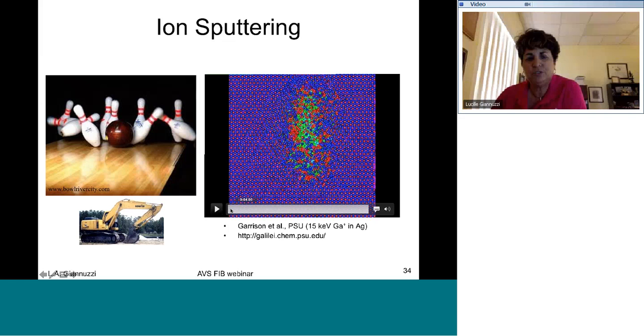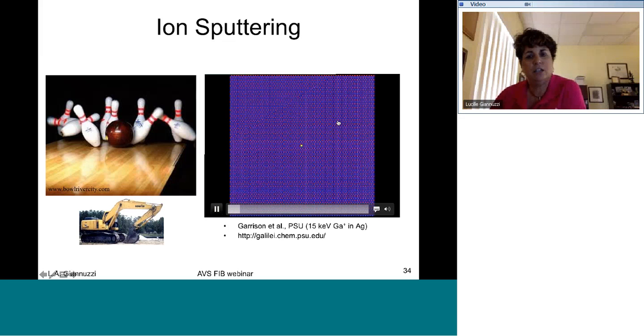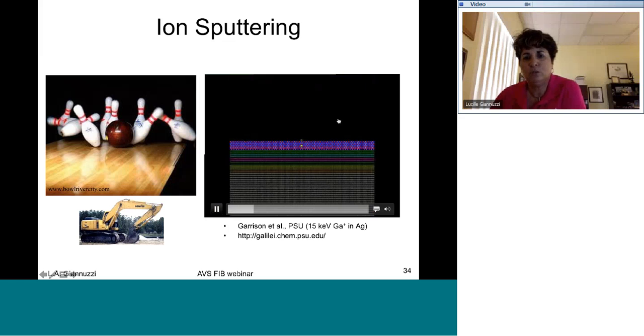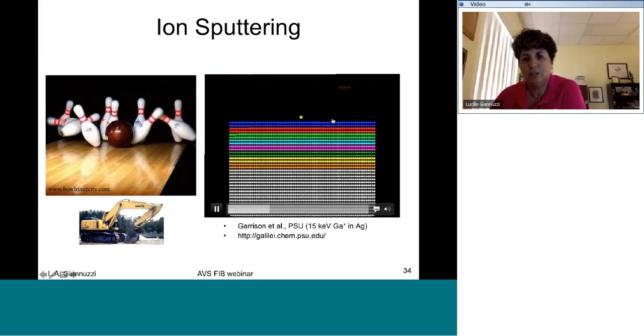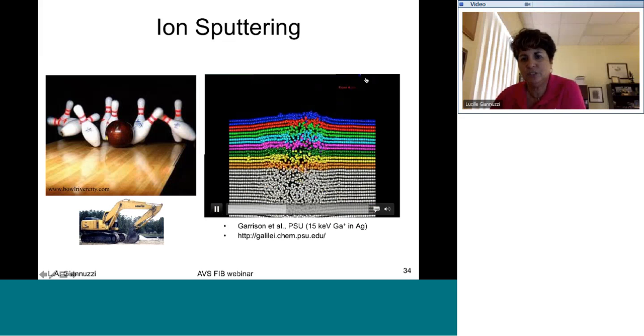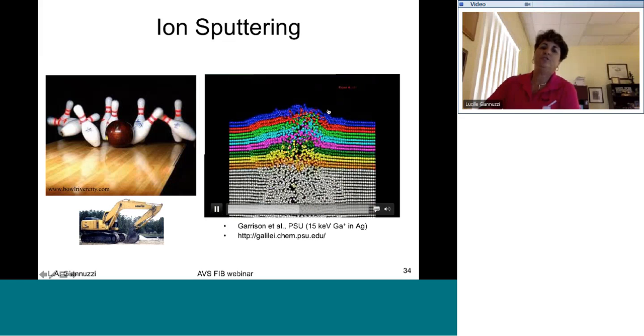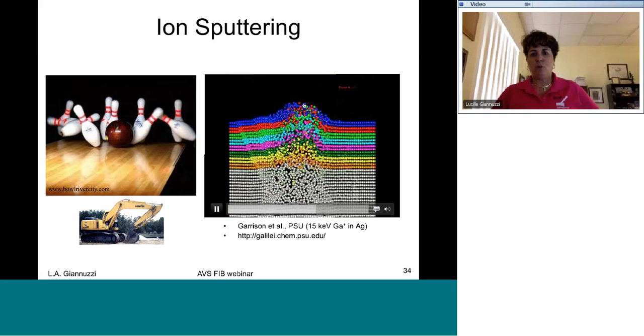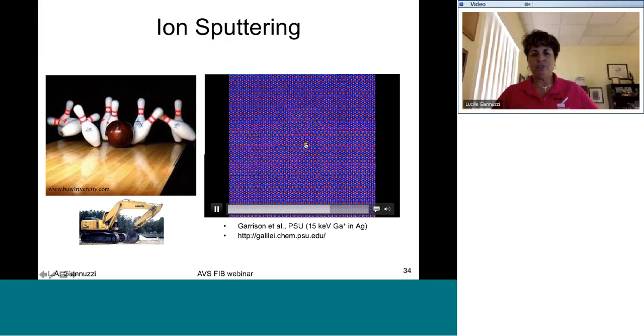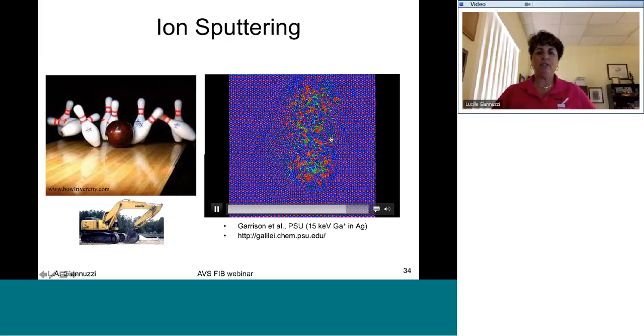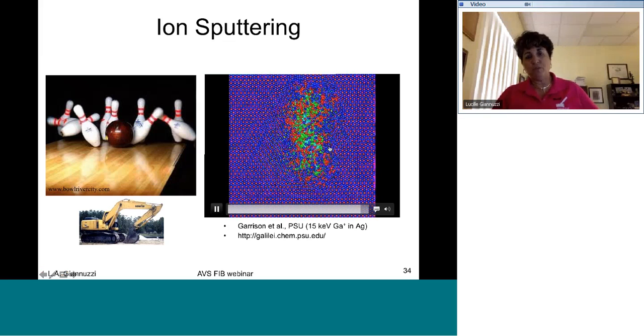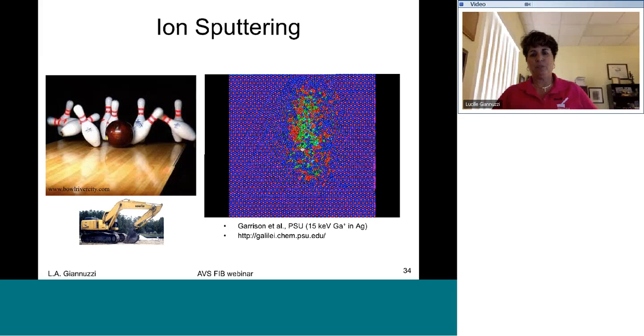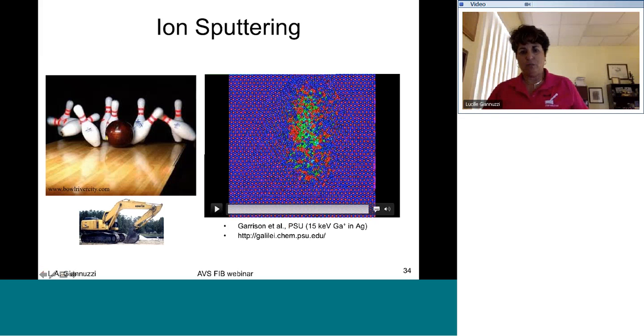And let me play this again for you, because I want you to concentrate on a blue atom that's going to come in, going to come out right about here. There. You see that go off there? The one thing that you notice right away is that where the incoming ion entered the sample surface and where the outgoing recoiled atom moved from the surface were two different locations. So people would always ask me, well, I've got this 2 nanometer resolution ion beam. Why can't I mill a hole that's 2 nanometers wide? And this is the reason.